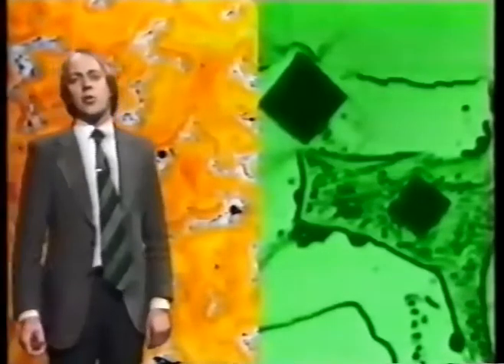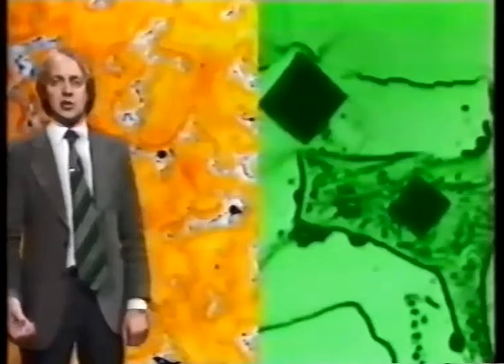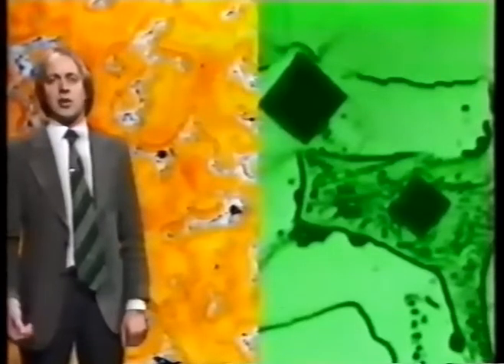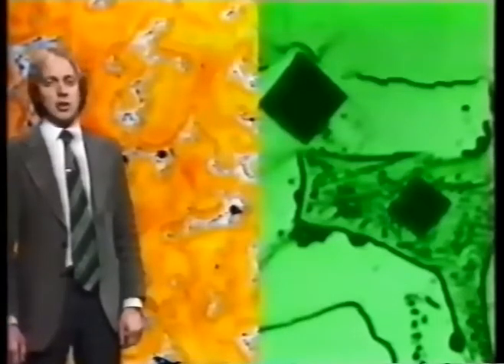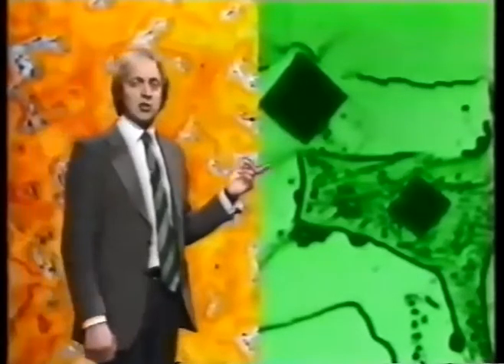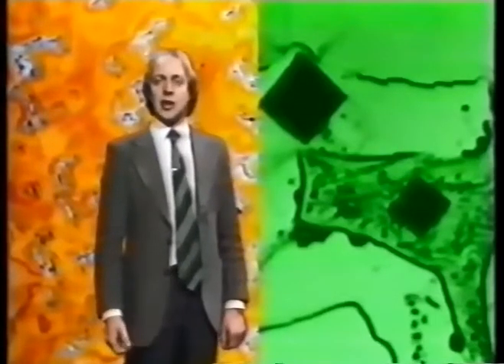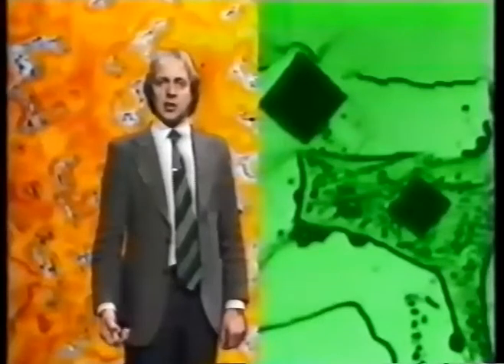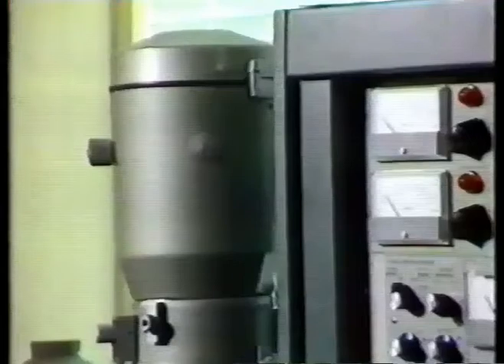So although the overall chemistry of our two bearings is the same, their performances were very, very different. Etching has revealed blue areas in the old bearing which were much more frequent than in its replacement. And our microhardness tests have revealed that the blue areas were significantly harder than the surrounding matrix. So although the overall chemistry is the same, these results suggest there are variations in microchemistry. And in order to examine these, we need to go to scanning X-ray analysis techniques.